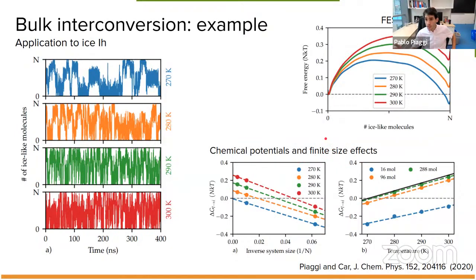So using the equations that I described in the previous slide, we can compute the chemical potentials and study also the finite size effects. That's something that I would like to highlight. So if we study the chemical potentials as a function of inverse system size, we see that there's a strong dependence. So finite size effects are very important. But we can yet extrapolate very well to the thermodynamic limit.